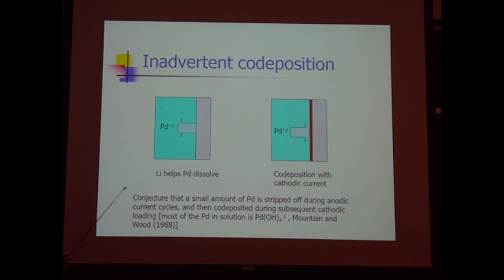And if the inadvertent co-deposition happens at 0.95, then by accident, you're making the vacancies. So this is the situation in SRI. It turns out in Fleischmann-Pons' experiment, I drew attention on Monday to a palladium reference electrode. Fleischmann and Pons were the only ones getting positive results to do that. Caltech was the only other group to run with a palladium reference electrode, and they didn't see anything.